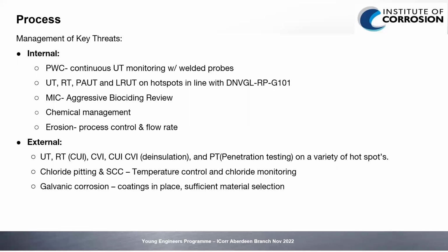Externally, we've got similar inspection activities, but on the CUI, we recommend radiography along with close visual inspection following de-insulation, or penetration testing if we don't remove insulation there. Other threats externally, we've got the chloride pitting. We believe discussions with the instrumentation engineers to discover if we can lower the operating temperature going forward, and that should also reduce the OPEX. And also for the stress corrosion cracking, we believe some chloride monitoring is required. In terms of the galvanic corrosion, we believe inspection of the current coatings in place and to determine if there's sufficient material selection right now.